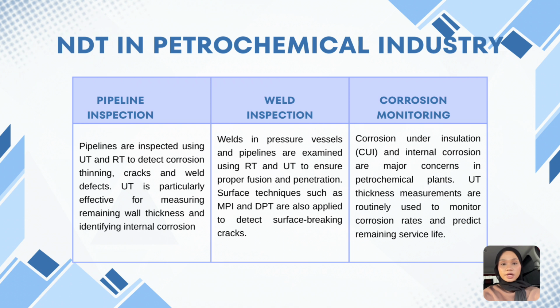Next, this slide shows how non-destructive testing is applied in the petrochemical industry. The first is pipeline inspection. The pipelines are inspected using ultrasonic testing and also radiographic testing to detect corrosion, cracks, and also weld defects. Ultrasonic testing is especially effective because it can measure remaining wall thickness and also help to identify internal corrosion.